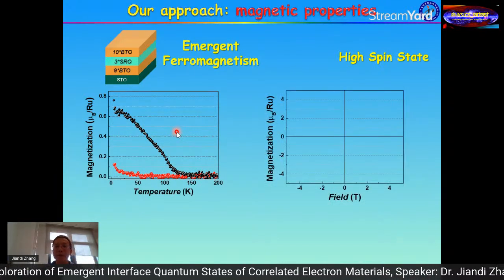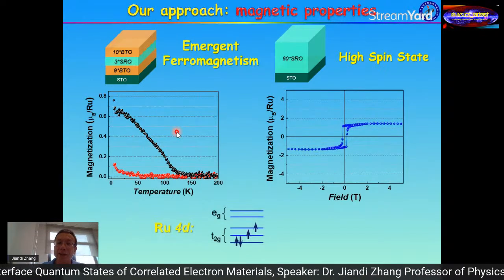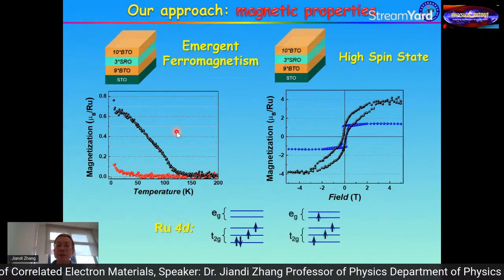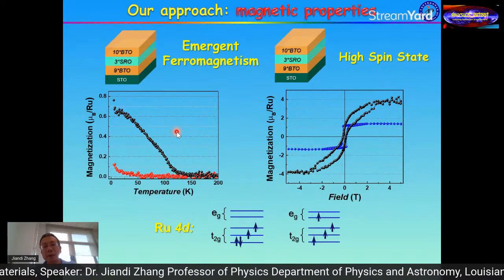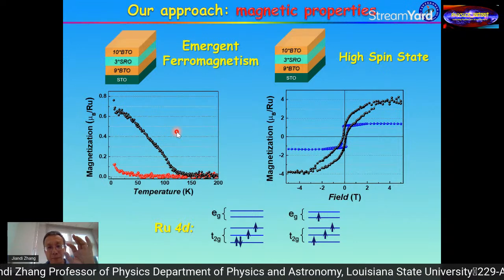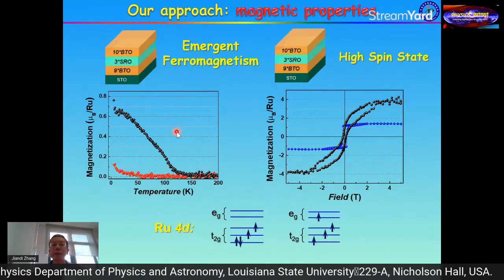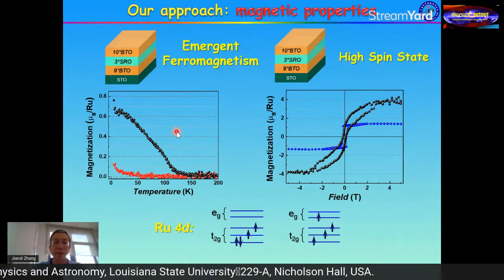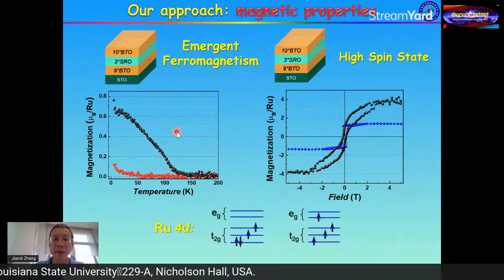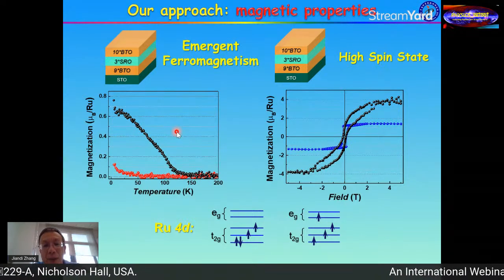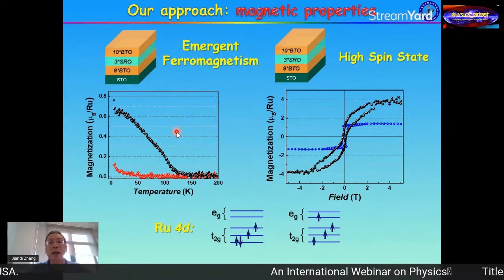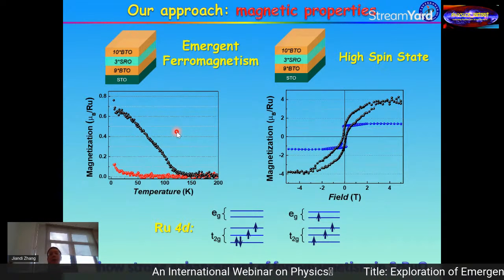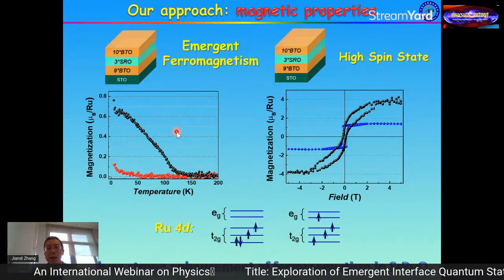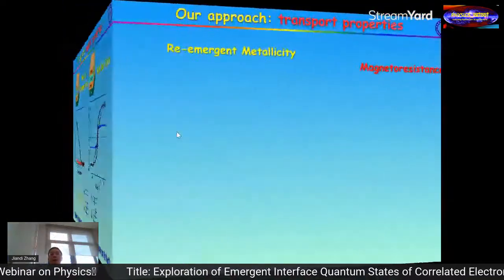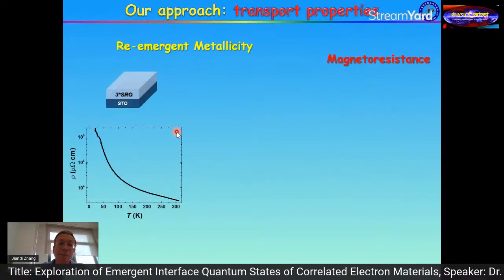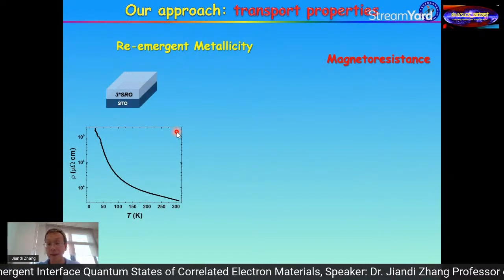First, second, look at the detail of that. And you find out this is because you not only create this magnetic layer, but you also change the microscopic electronic structure inside this strontium ruthenate. It actually turns the so-called low spin state to the high spin state. Okay, so all the spins in each orbital of the electrons line up perfectly together.